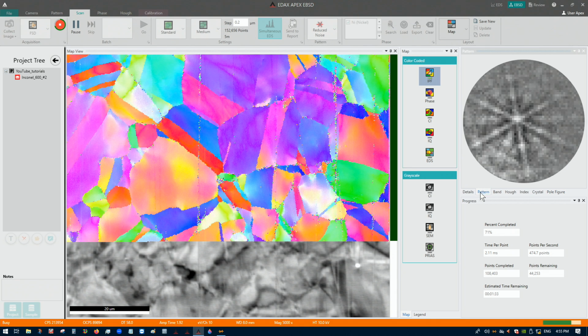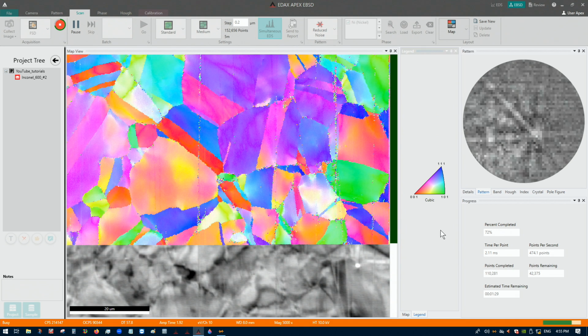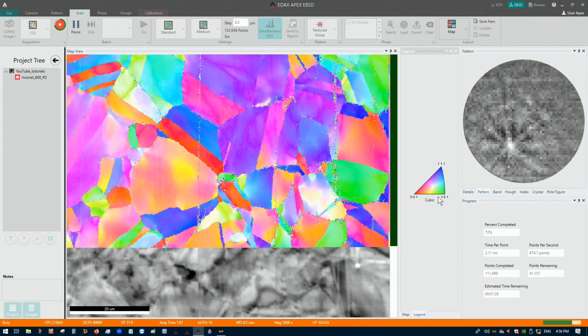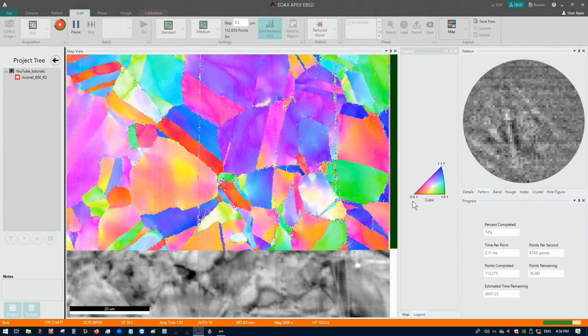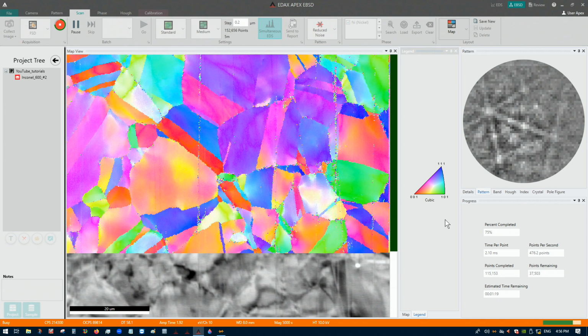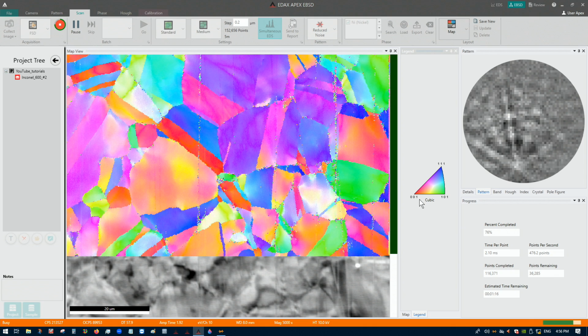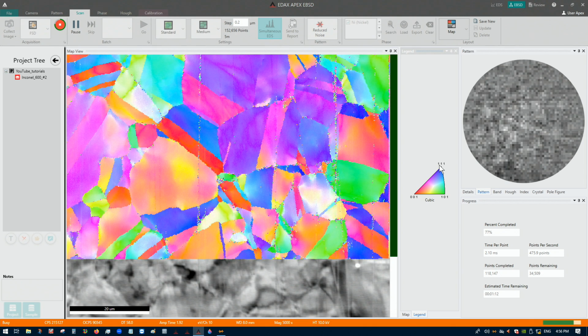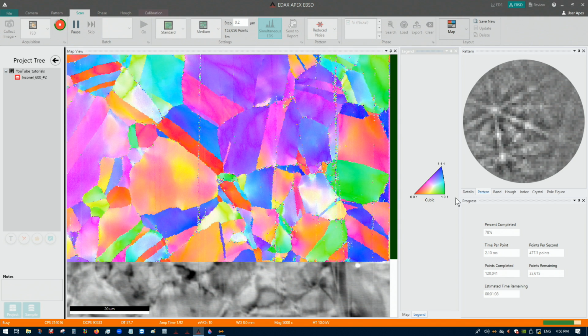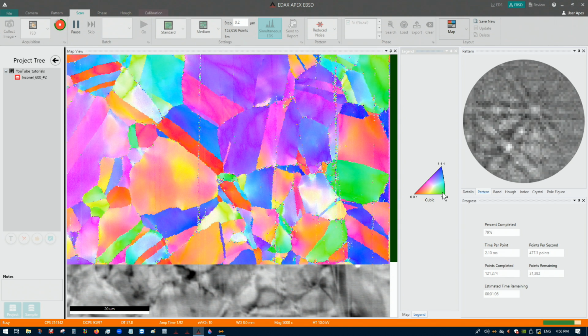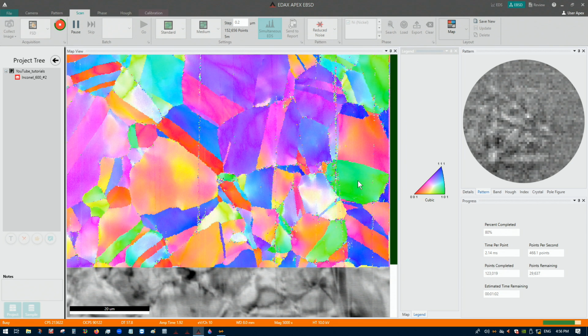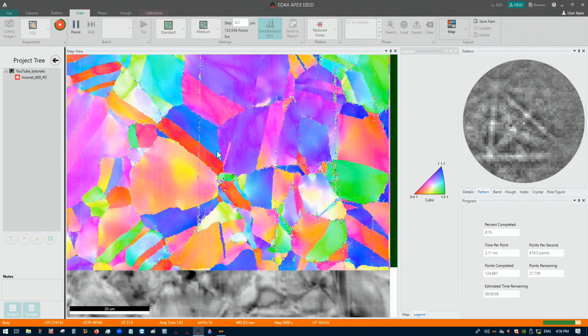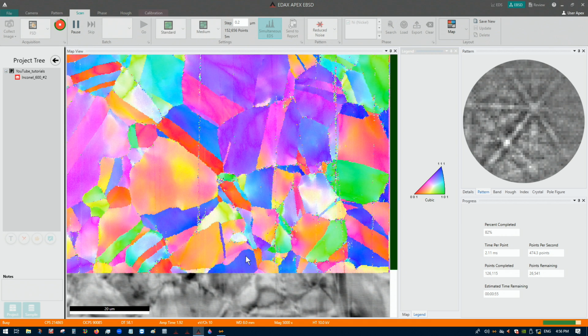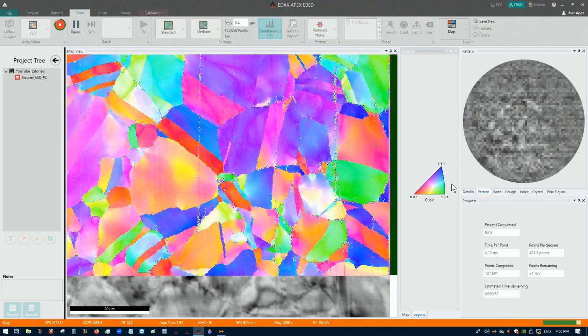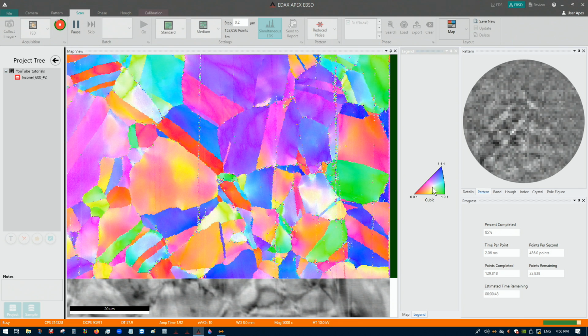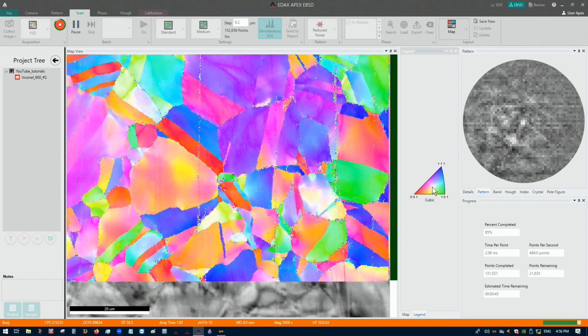If we come back here to just the live pattern, and then we go to legend here. So for the IPF, in a cubic crystal, all of our orientations are contained inside this one triangular snippet of the stereographic projection. Okay, so red means perfectly 001, blue is perfectly 111, and green is perfectly 101. Okay, so this refers to the set of planes that is parallel to the surface. Right, this is deep in the green, so this is probably close to 101, and then we have some nice red here, which is 001, and some nice dark blue here, which is 111. And so any color combination of these can represent any of the in-between colors, okay, which is pretty neat.